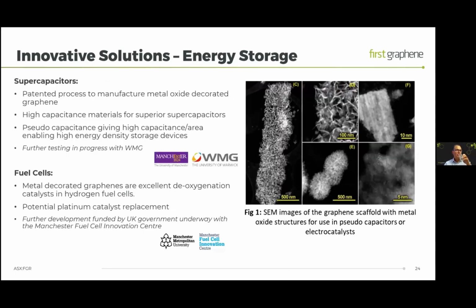And we continue to look at energy storage materials. Our focus here is on the emerging supercapacitor market. And we have a really nice set of materials, which are metal oxide decorated graphenes. The technology was developed at the University of Manchester by Professor Kinloch and Professor Dryfe. And what these materials are, they're graphene scaffolds. So if you look at the top center image on the right, these are almost honeycomb graphene scaffolds with nano-sized metal oxides deposited onto those surfaces. So they're ideal substrates for pseudocapacitance.